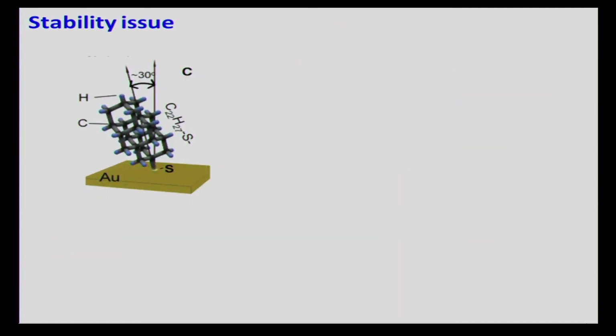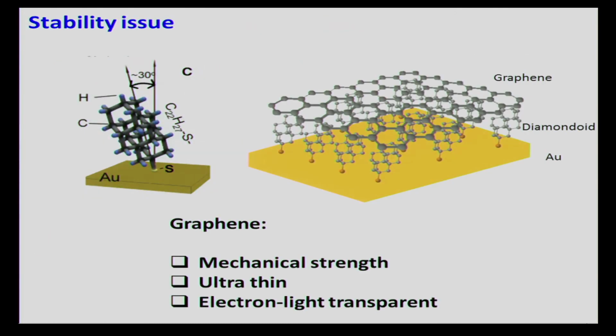So what we can do then is take the diamondoid and bring in another, well, its cousin, another type of carbon material, graphene, and lay them together. Graphene is a very dense monolayer of carbon. It's mechanically robust such that it confines these diamondoid species on the surface, not letting them fly away from the surface into the vacuum.